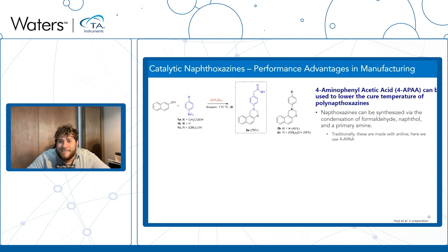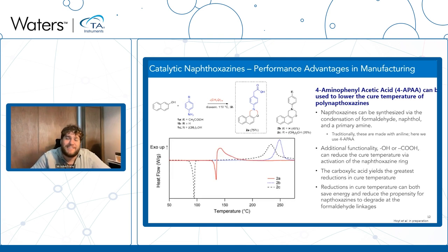So what Caroline did is once she made these materials, sorry, I keep clicking my arrow instead of in the platform itself. She made these materials and she tossed them on a DSC to see what their cure is. So the blue dotted line here is a typical petrochemical naphthoxazine resin. And what you see here is that you slowly heat up this material itself. And then eventually, once you get around 250°C, it will go through the cure. And it will have an exotherm, it will complete the cure, so on and so forth.